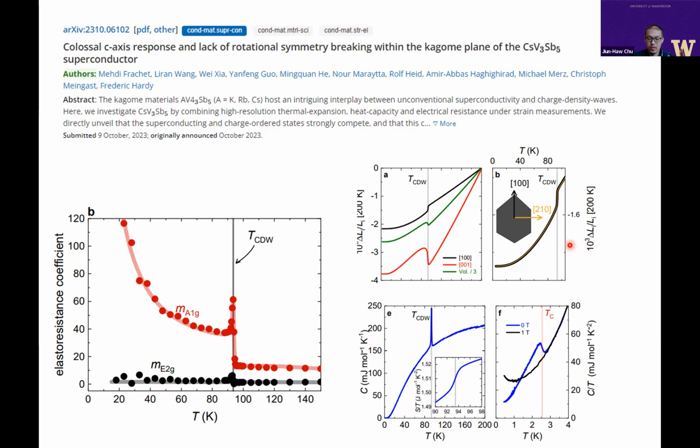That means that both the shear strain epsilon xy and epsilon xx minus epsilon yy are the two components of this two-dimensional array. So that means that you can point to any direction with respect to your crystal axis in plane, and you'll get the same linear response. The nonlinear response will be different, but the linear response will be exactly the same, no matter which direction you're pointing, if there's an anisotropic response there.